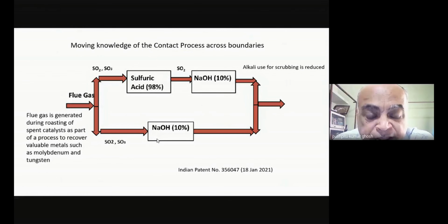The moment I saw SO2 and SO3, obviously my mind went to what? Contact process. And I said, what do we do in the contact process? We do an absorption, the double contact, double absorption process, where we take the SO2 and SO3 and pass it into sulfuric acid, and it becomes like oleum. Because SO3 is very strongly soluble in sulfuric acid. It will form more sulfuric acid. But SO2 does not have high solubility in sulfuric acid. So that's how you regenerate pure SO2 from SO3 and continue with your contact process.